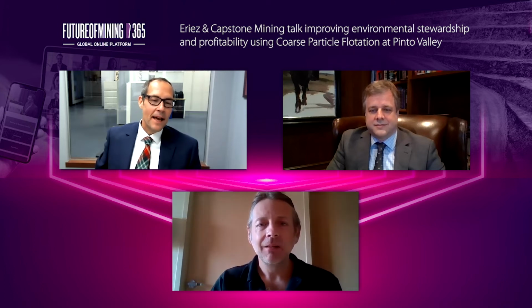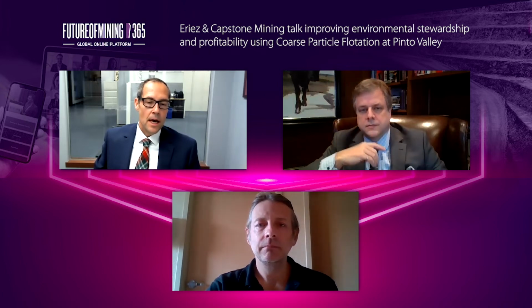Thanks, Paul. We often get that question, and it's a good question, because if the HydroFloat used the same principles as conventional flotation, we wouldn't expect a radical improvement when we just refloated them using the same technology. The vast majority of flotation operations use stirred tank flotation cells, and they've only been improved incrementally over the last 100 years or so to their present plateau in performance. As a reminder, a mechanical cell uses an impeller, and the shaft work creates shear to make bubbles and keep the solid suspended. And that uses a lot of energy, on the order of a kilowatt per cubic meter of tank size. And these tanks are very large, upwards of 300 cubic meters. And there's many of these in the plant.